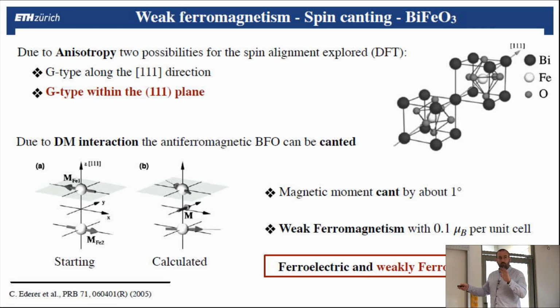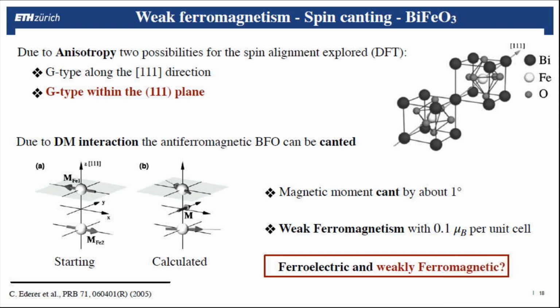So let's say we start here. This result is also numerical, from the Schrödinger equation solved numerically. And we said that here you have the 1-1-1 direction, and the spins should be perpendicular to that direction in the plane. So let's start from this. We can run the calculation, and we will get this final result. And you can see that in the final result, they are not perfectly aligned like here, but they are canted a bit, by about 1 degree. And this results in a weak ferromagnetism of about 0.1 Bohr magneton per unit cell. So it's a tiny amount, but still it's a small net magnetization.